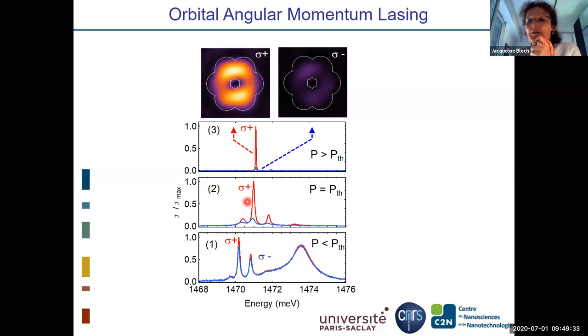So actually what some colleagues told us is that if we were to pump the system with a pulse and we would get a pulse laser, probably the gain medium would not have time to depolarize completely and we would get a much higher polarization ratio. So I think the depolarization is of the order of 10 to a few 10 picoseconds.